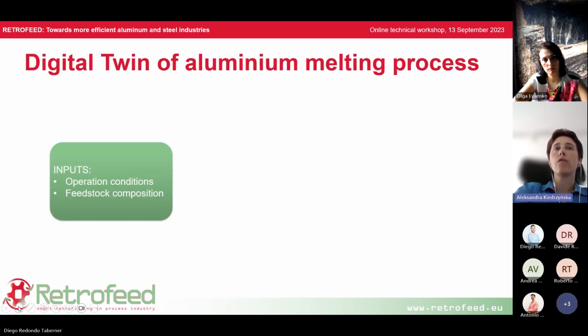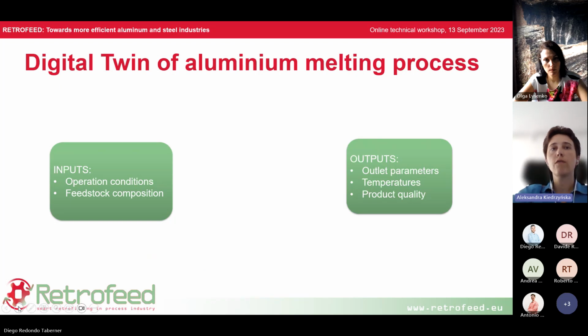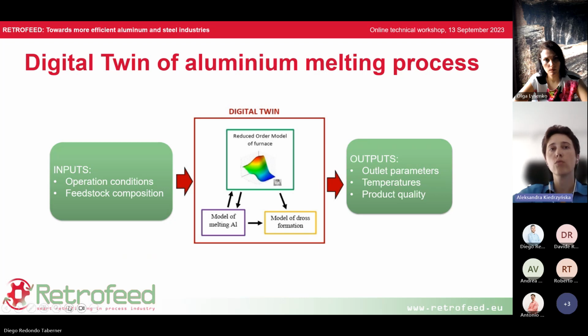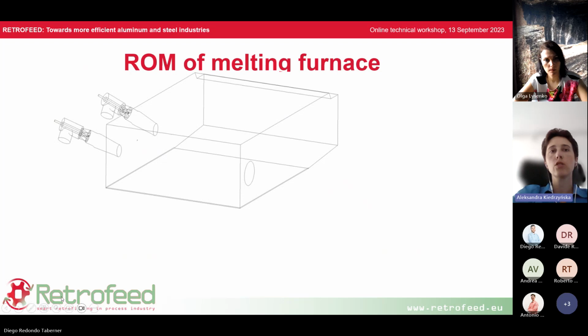In the case of the aluminium melting process, the inputs to the digital twin are operating conditions such as power of fuel, temperature of air, air to fuel ratio, and oxygen flow, and parameters concerning the composition of feedstock loaded to the furnace, such as total mass of aluminium sources, ratio of scraps, and ratio of contamination to scraps. The outputs are parameters such as temperature, species concentration, and emissions.